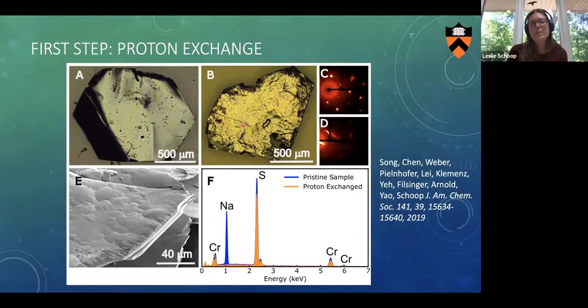But it's fine. We take it to the EDX to measure the chemical composition. And she found all the sodium is gone. Great. That's what we wanted. She puts it on an X-ray diffractometer, and if she shines the X-rays through this crystal, she gets nice crystalline diffraction spots. But if she shines the X-ray through the side of this crystal, she gets these streaks. That's not good. That means there's not that great crystallinity between the layers anymore. And so because of this, we couldn't solve the crystal structure with the X-ray.